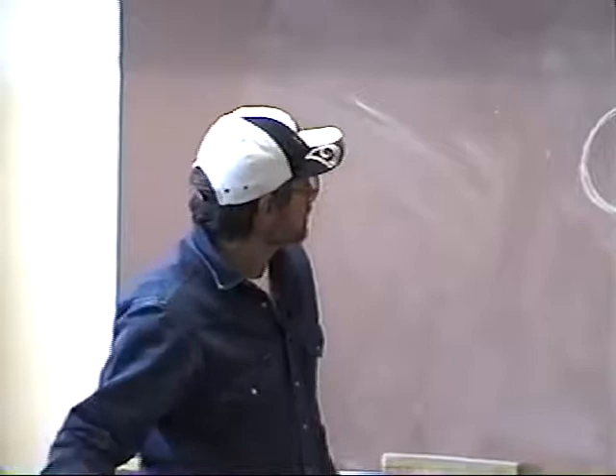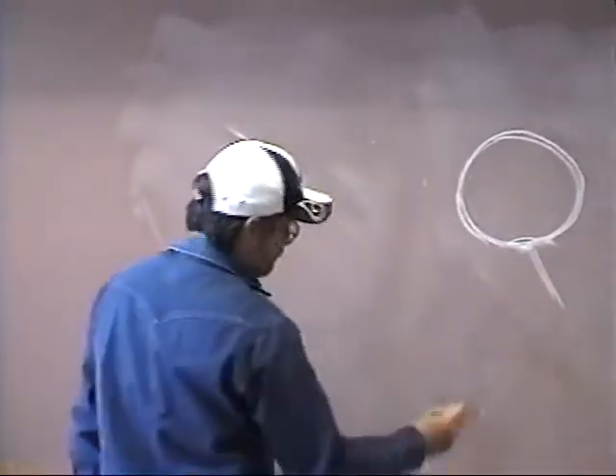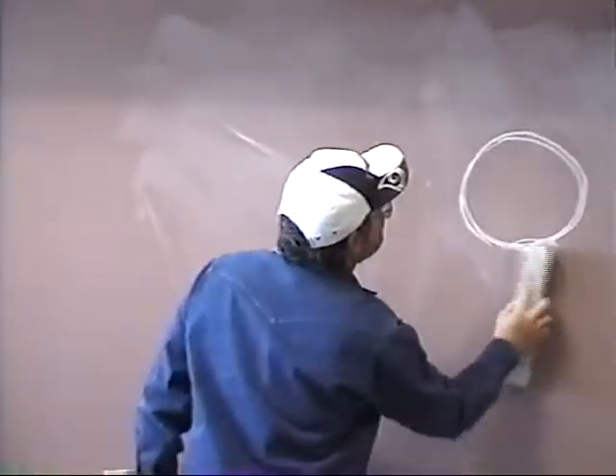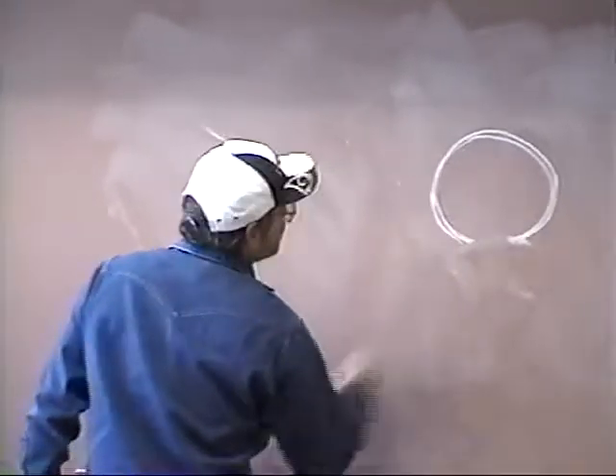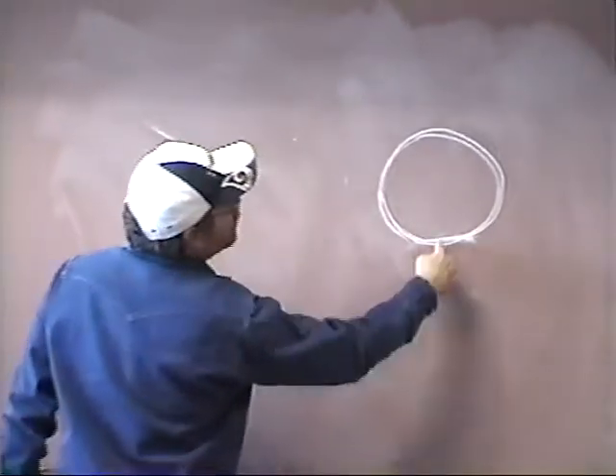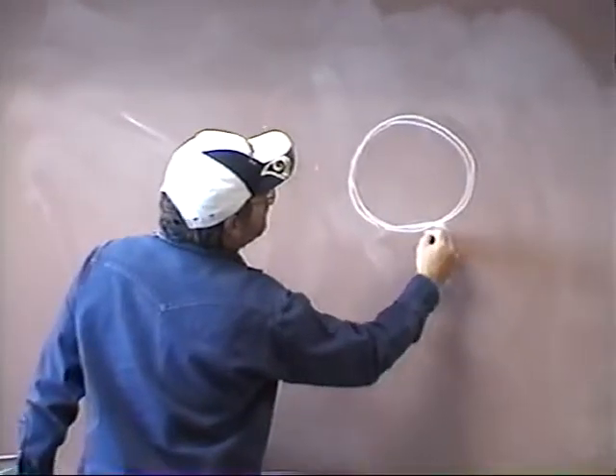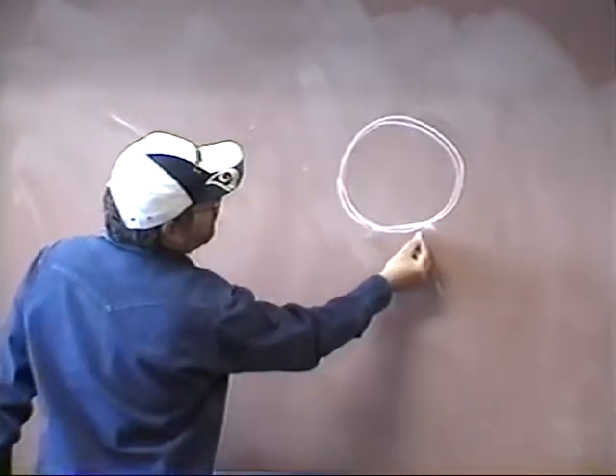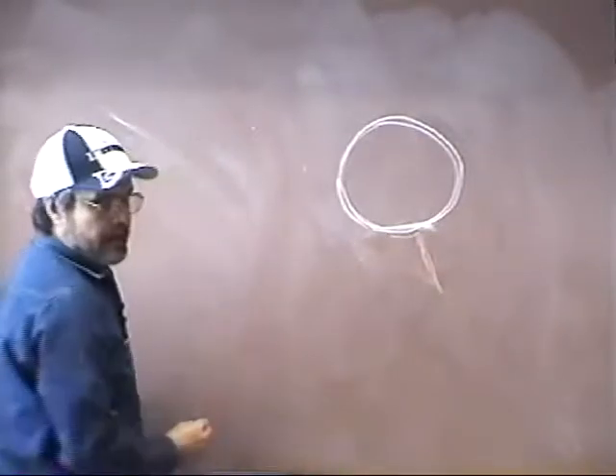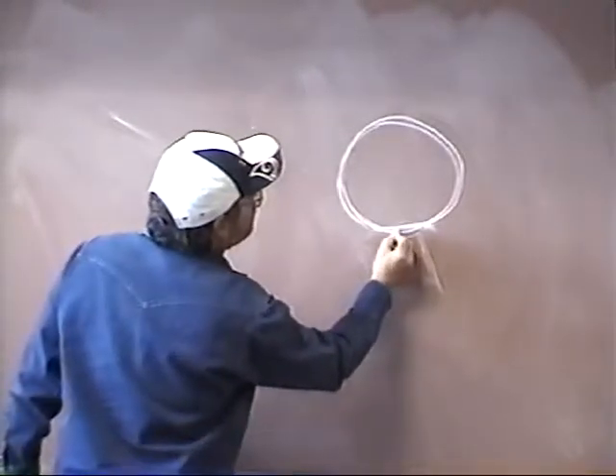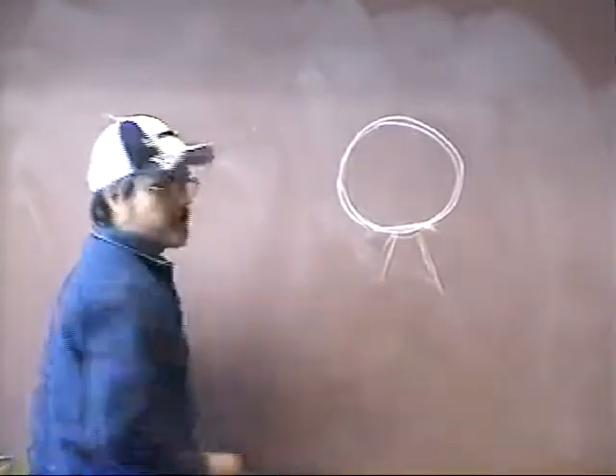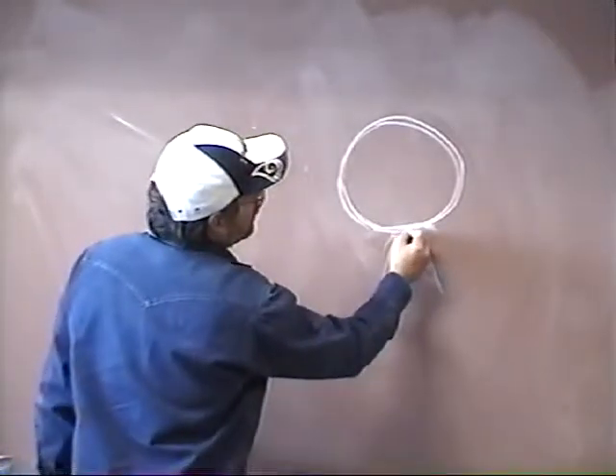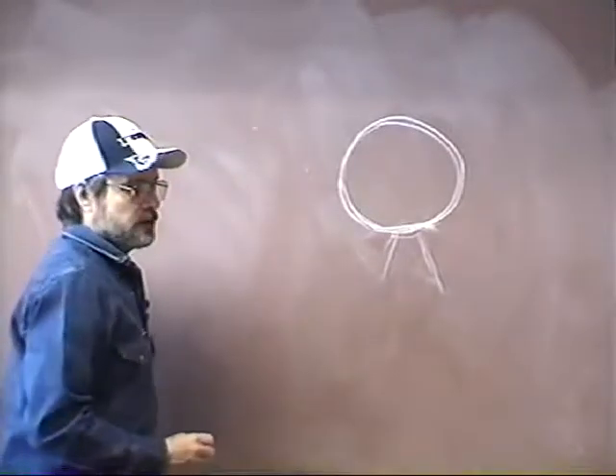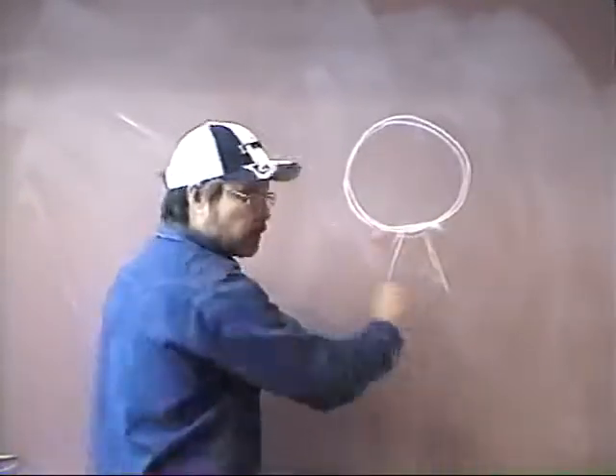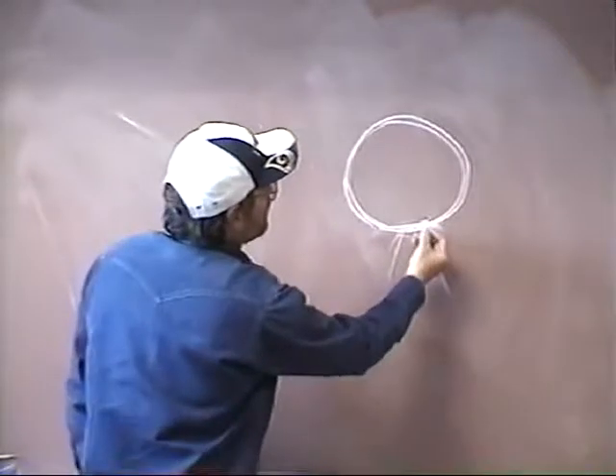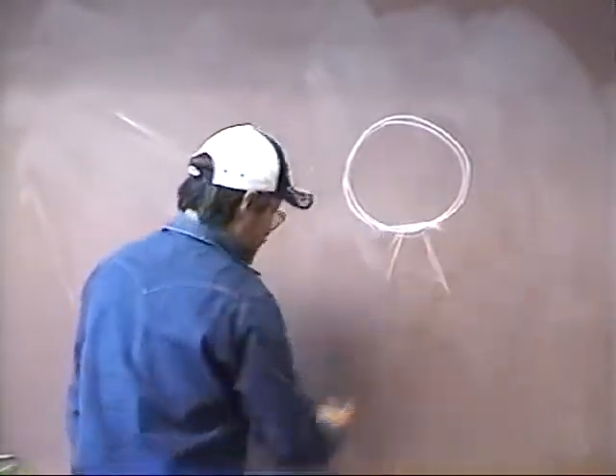So what they're telling us is, if I'm going to put a tack in here, draw another picture here. If I'm going to put my tack right here, I'm going to strike my arc over here. I'm going to allow it to stabilize as I'm coming back. When I get back, I'm going to shove that into a short arc and go ahead and deposit my tack. That way, if I have any arc strikes or any contaminants, it's going to burn out as I come back over it. So you're going to strike out in front, drop back, shorten your arc, put your tack in.